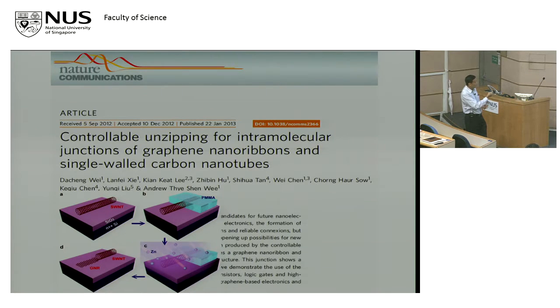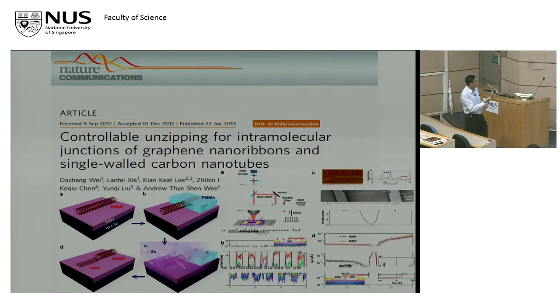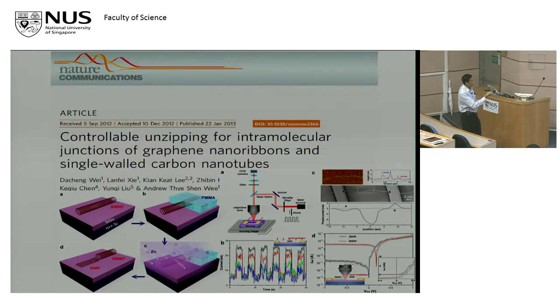So you have a metal-semiconductor junction, and physicists will know that you can make devices and photo switches with such junctions. So we demonstrated that in this paper, which is quite nice. But of course, it's possible to do on a single layer, but it's much more challenging to scale up. But again, it was a demonstration of unzipping nanotubes to make graphene ribbons in part of your circuit. Okay, but I won't elaborate on this because, as I said, it's not the surface science approach, but just to let you know, we do some device work as well.